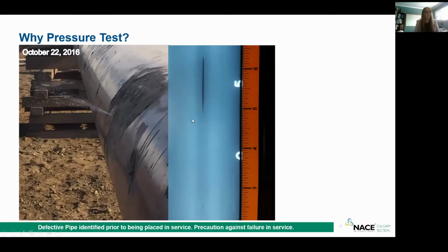And on the right here, you can see an X-ray, and this darker region is the long seam, and the black portion is actually the through wall long seam failure. So it's pretty important, before you pull an HDD, to have that 1 hour strength test confirmation that you don't have a defective pipe before you spend all that money pulling it through your drag section.